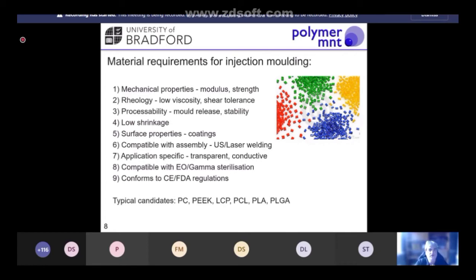We then also have to look at the rheology behavior of these materials in our processes as well. So the rheology is how easily do these materials flow in our molding process, because if the rheology isn't suitable, we won't get the material to flow into the microneedle cavities. We won't be able to achieve the tip sharpness that we need to ensure the penetration behavior. And so this needs to be considered at an early stage in the design process.